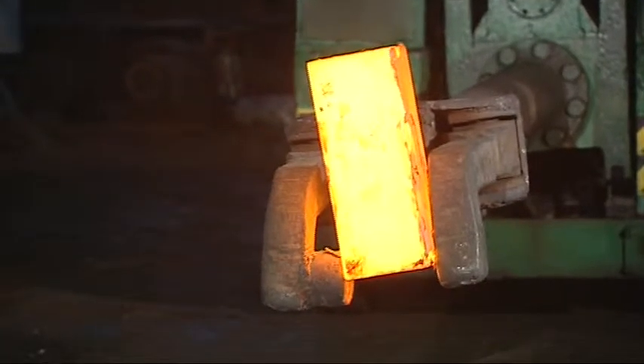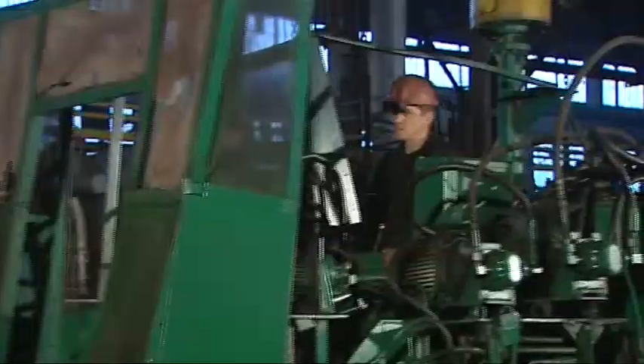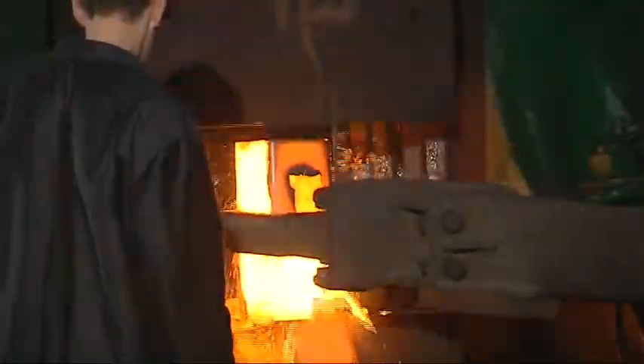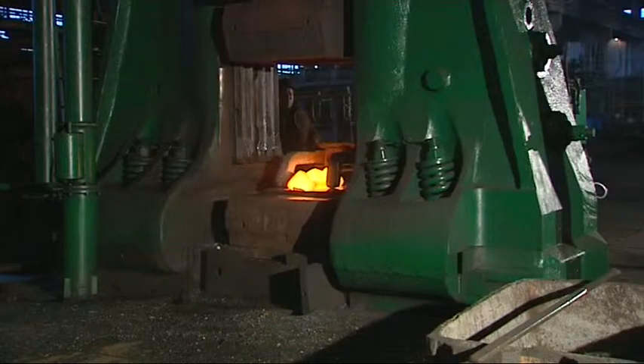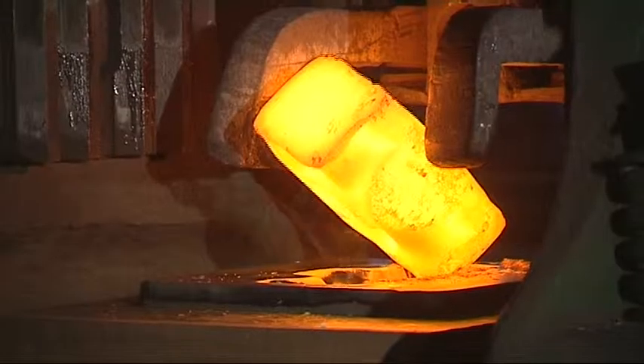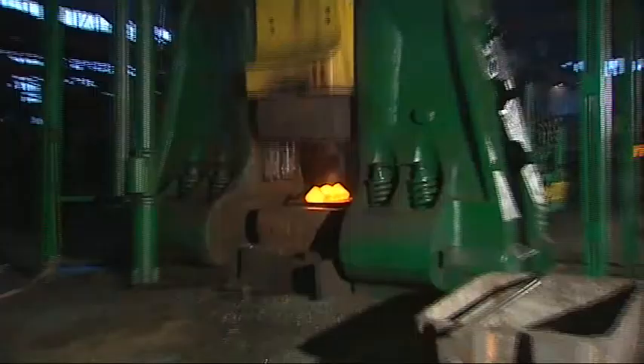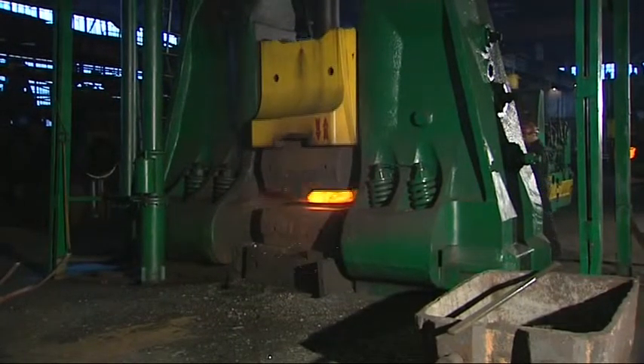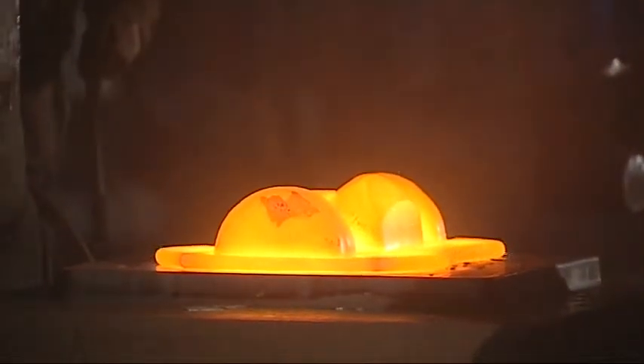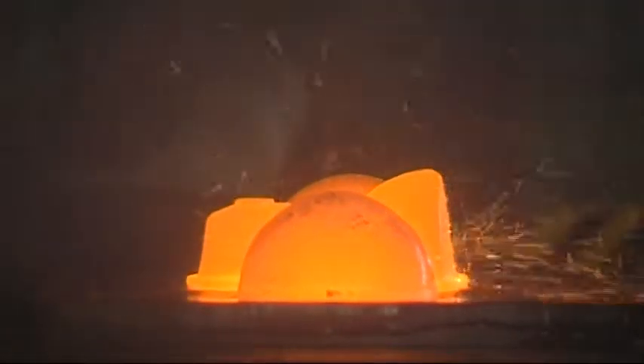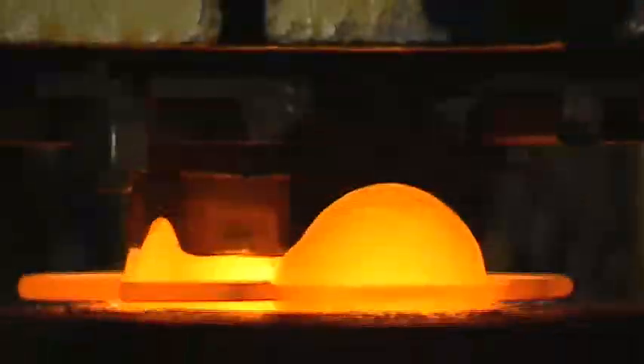There is also a department for die forging in the shop where a set of dropping hammers having weight of 1, 2, 5 and 16 tons is used. This wide range of hammer weights makes it possible to produce die-forged parts of various shapes with mass 300 grams to 250 kilograms. Billet is preheated in furnace, then die-forged on hammer stamp and spew is cut on a trimming press.